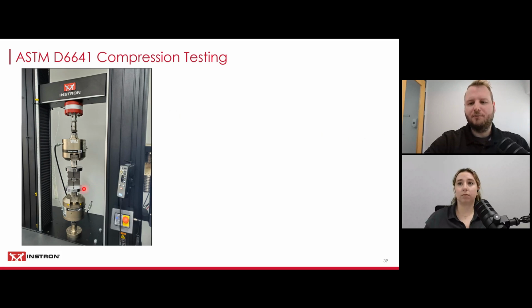You can see my load frame set up here on the left. It's a 100 kilonewton testing machine, the same one that Ashley was using for the tension testing, from our 6800 series. And it's equipped with those same hydraulic wedge grips, but in this case I am piggybacking fixed compression platens on those hydraulic wedge grips, and then you can see the ASTM D6641 fixture in between those fixed platens. The testing standard actually recommends using fixed platens as opposed to using a circle on top, which is still allowed in the standard, but the standard itself is recommending fixed platens.